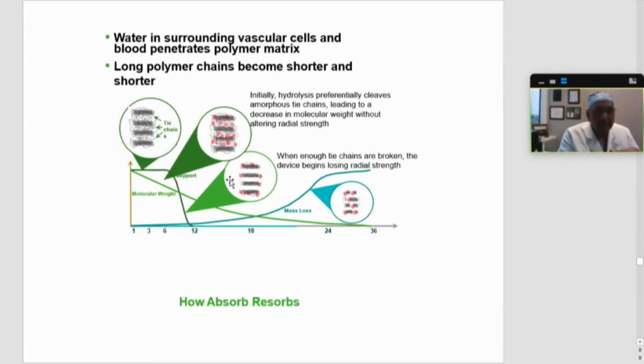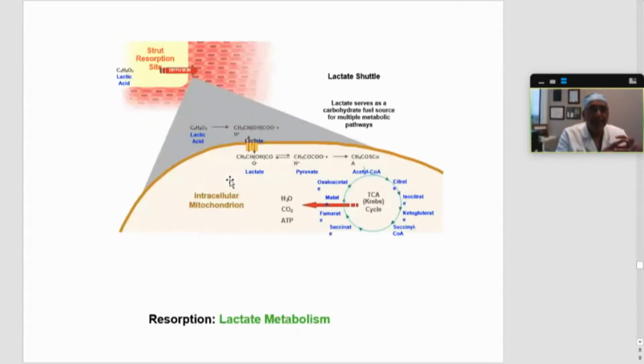And this is done via nothing but hydrolysis. So water in the surrounding vascular cells and blood penetrates into the polymer matrix. The long polymer chains become shorter and shorter. Initially, hydrolysis preferentially cleaves amorphous tie chains, leading to a decrease in molecular weight without altering radial strength. When enough tie chains are broken, the device begins losing its radial strength. And the good thing about a stent design like Absorb is that the absorption is not an inflammatory process, because it uses the lactate shuttle, which is part of the Krebs cycle. So there is hardly any inflammation with resorption of PLLA.